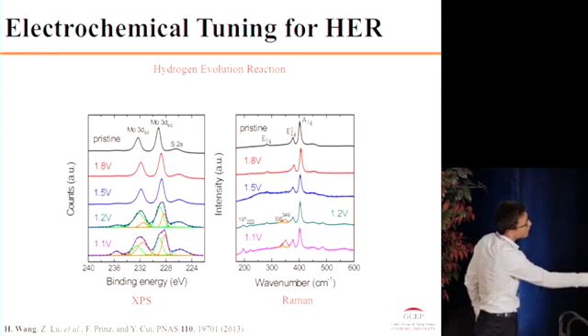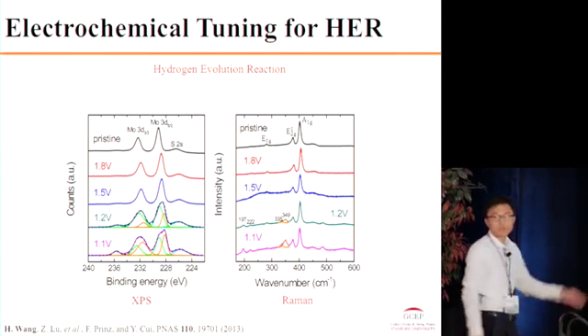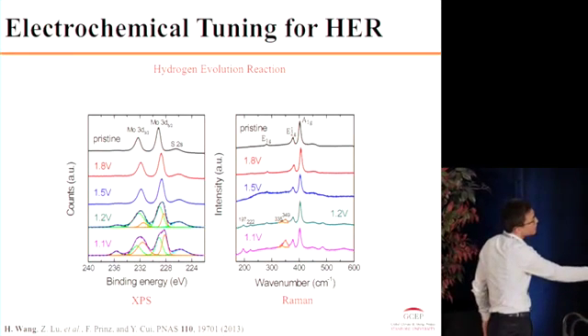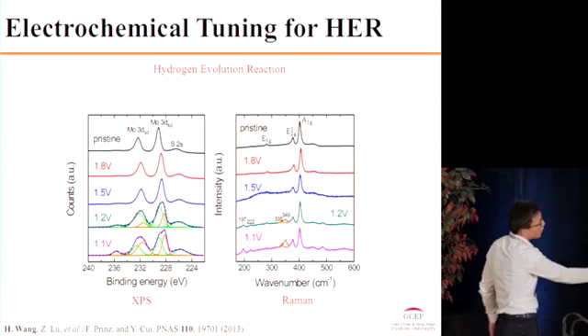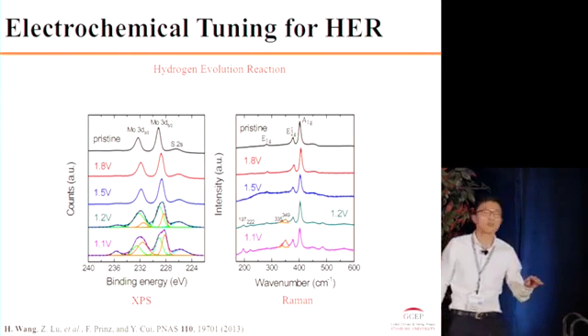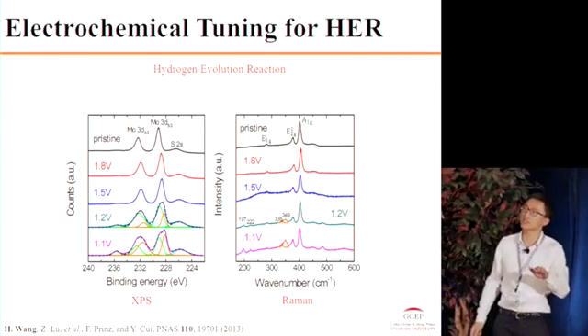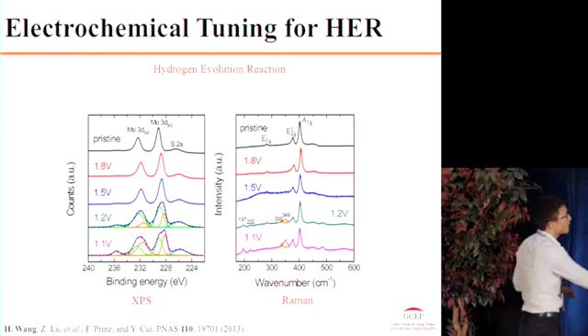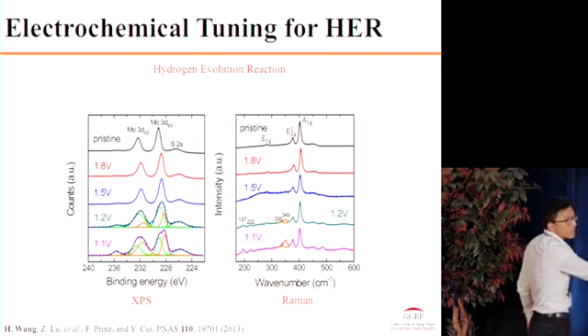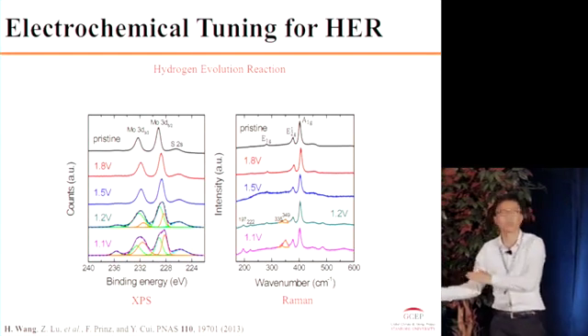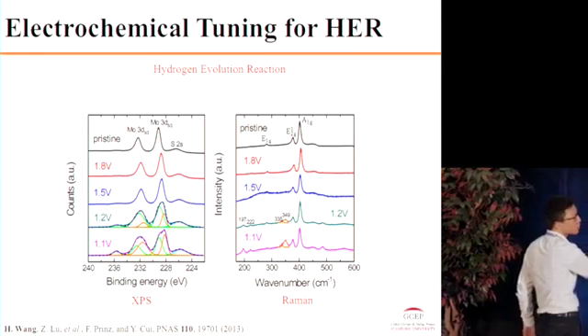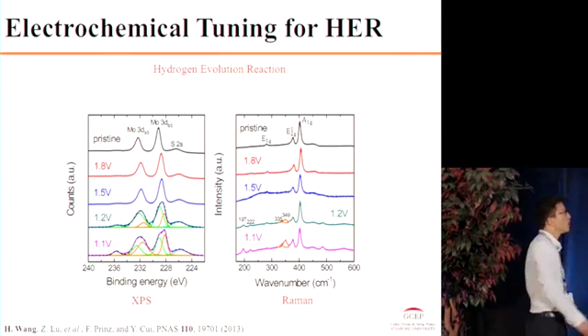So when you have a 1.8 and 1.5 volts lithiation voltage, you can see in the XPS that the oxidation state of moly gradually shifts towards a lower binding energy, which represents that the oxidation state of moly is reduced. But when the phase transition happens, one new peak comes out, which represents the 1T phase, and it gradually increases in ratio compared with the semiconducting phase. And the Raman spectroscopy also shows the coming of a new peak.